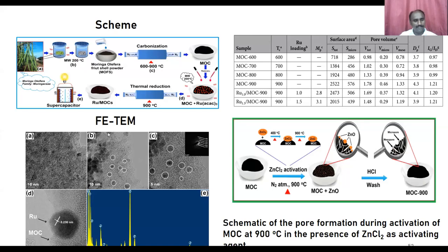This is the TEM image, and you can see the bare image of the carbon material. The white circles indicate the ruthenium nanoparticles deposited on the high surface area of the carbon material. You can see in this image the carbon is holding the ruthenium particle. This is the carbon layer, and this is the ruthenium particle. It tightly holds the particle during the activation process and also the thermal treatment.